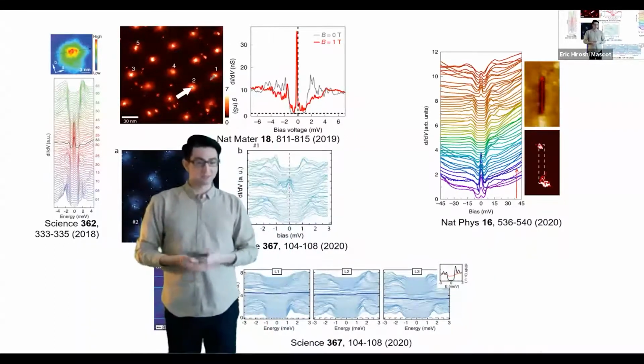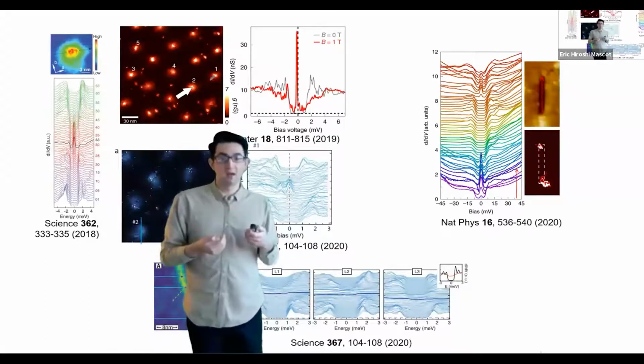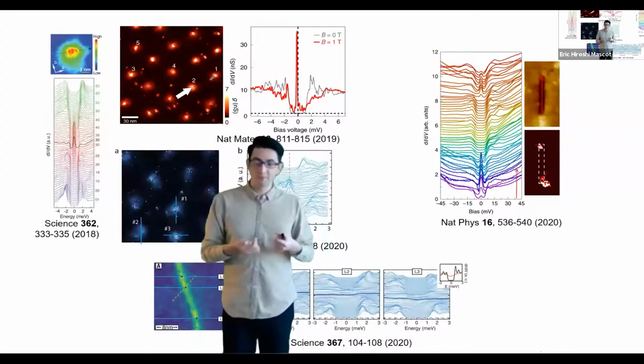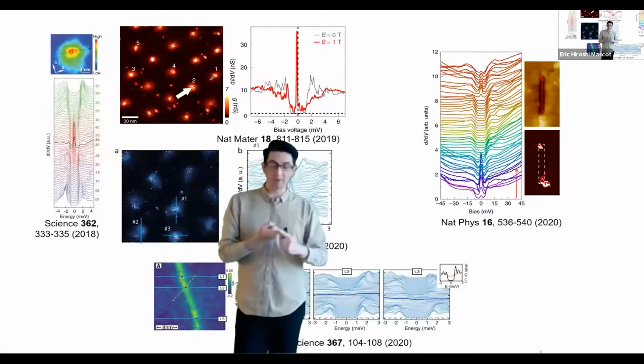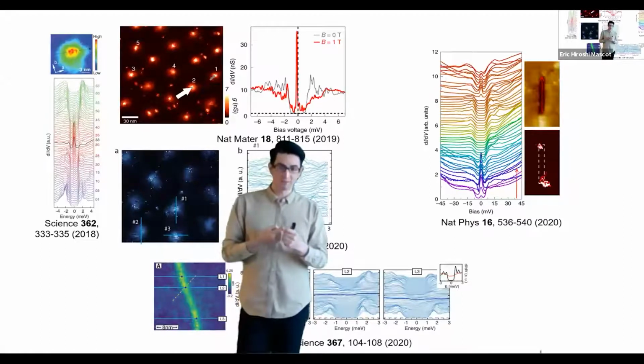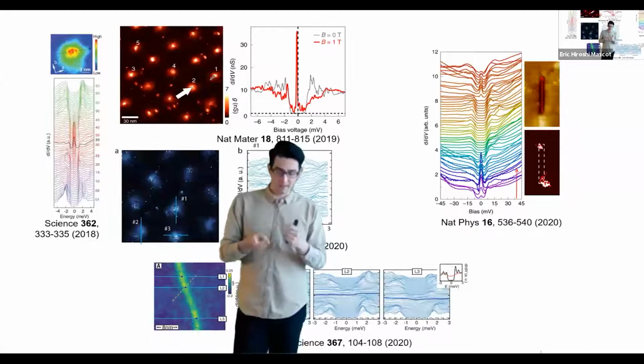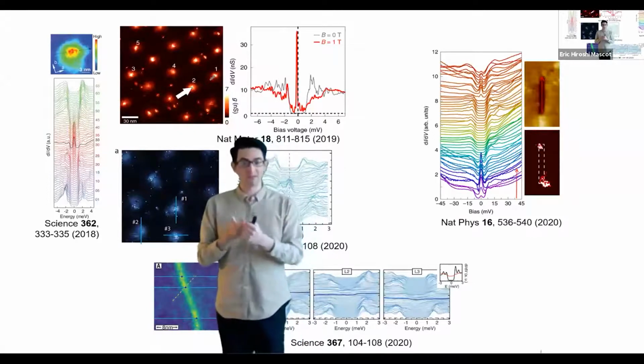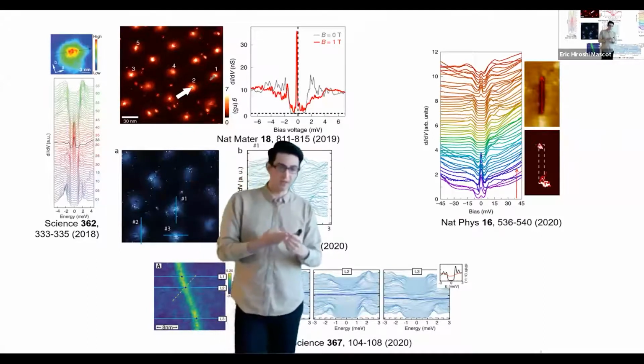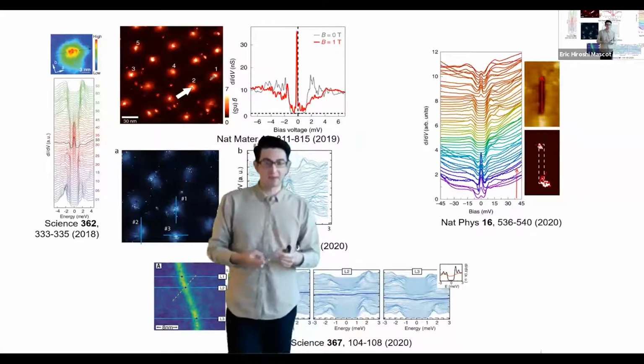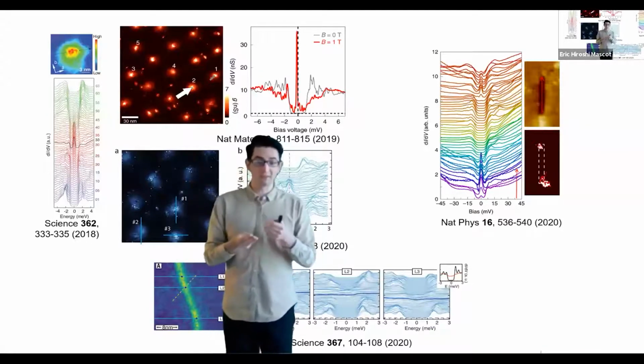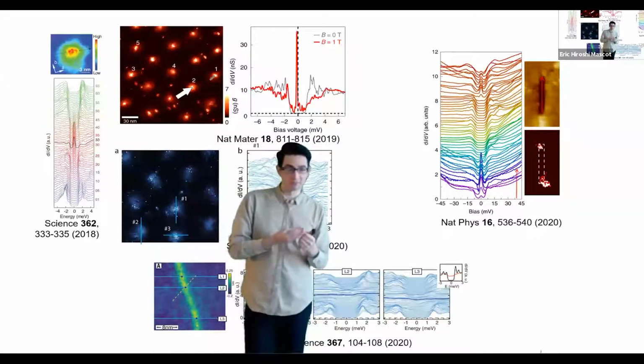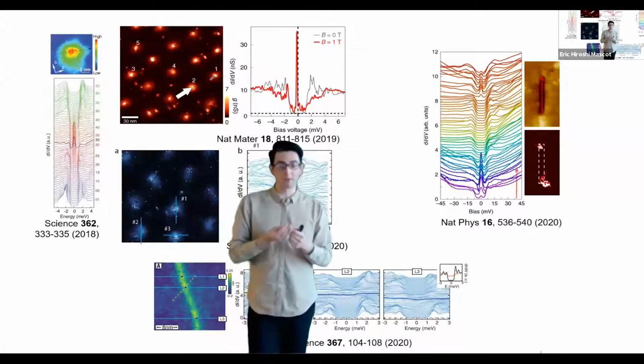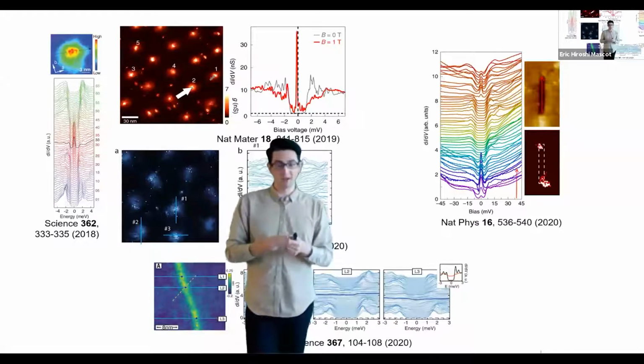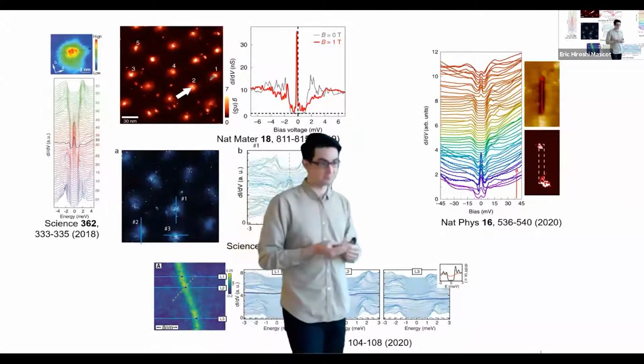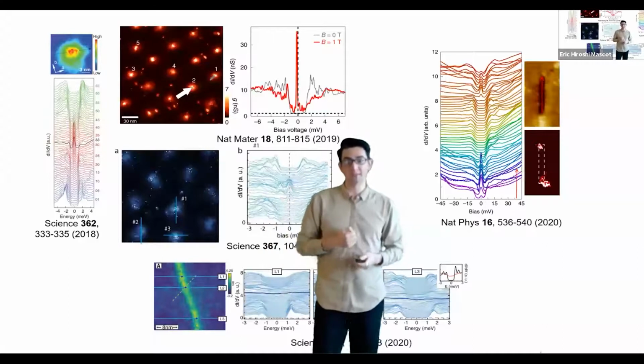And to explain the origin of this superconductivity, we can imagine that we already have the s-wave superconductivity, and we have a surface, and so we have a Rashba spin-orbit interaction. What's missing is a magnetic order. But recently, there has been evidence from ARPES experiments that there is a ferromagnetic ordering on the surface of FeSeTe.